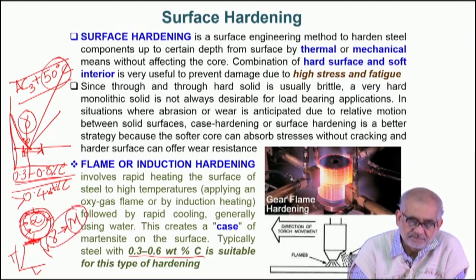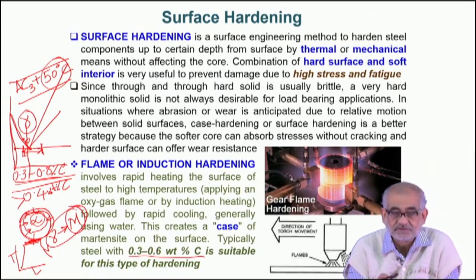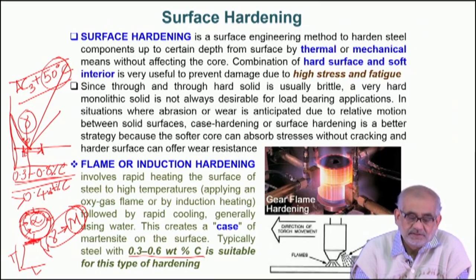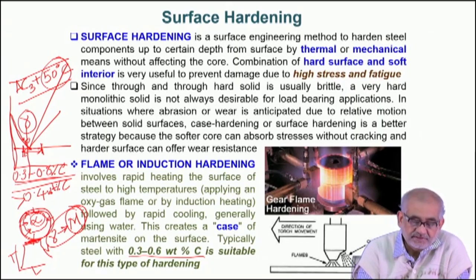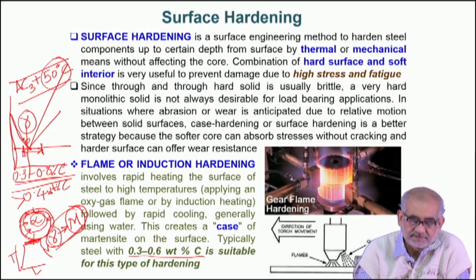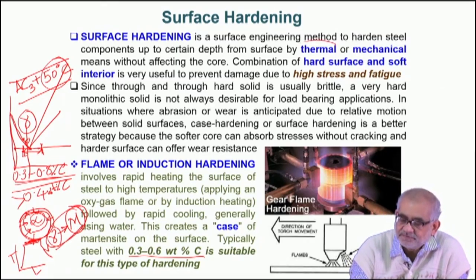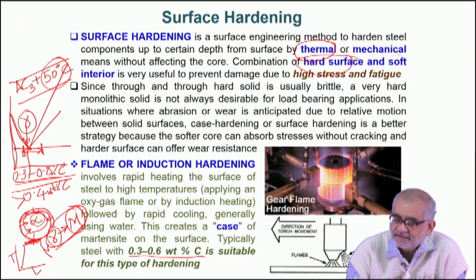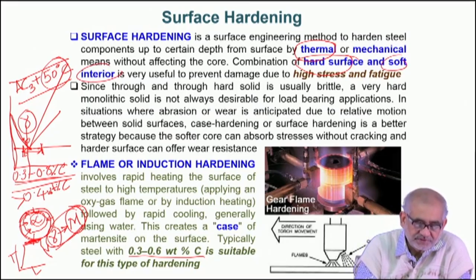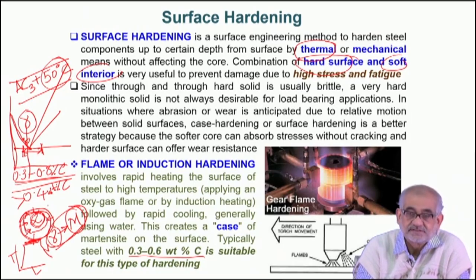The strengthening here is due to martensite, as compared to previous surface deformation-induced processes like shot peening or laser shock peening, where we introduced plastic strain and dislocation density to create residual compressive stress. Here the process involves a solid-state phase transformation wherein austenite transforms to martensite. This is primarily a thermal treatment: we want a hard surface and a soft core, because the ferritic core can absorb energy including impact, while the surface resists deformation due to wear, abrasion, erosion, and other surface damage.